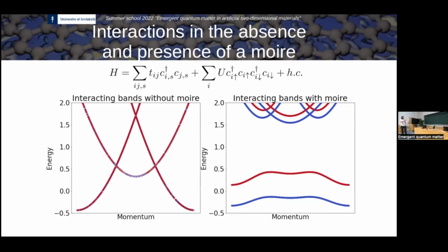And this is of course the typical case that you have in a TMDC, a doped TMDC. If you take a TMDC, the system usually remains a semiconductor, so it doesn't become magnetic, even though you have a certain carrier density, just because the density of states of your system is not large enough. But now when you go to the twisted system, then suddenly your bandwidth is much smaller, your density of states becomes much bigger, you fulfill the Stoner criterion, and then you see that a correlated state appears, a gap appears in the self-consistent solution, and this becomes a Mott insulator. So just with the twist angle, you go from a doped semiconductor that has metallic behavior to a Mott insulator, just by the reduction of the bandwidth.